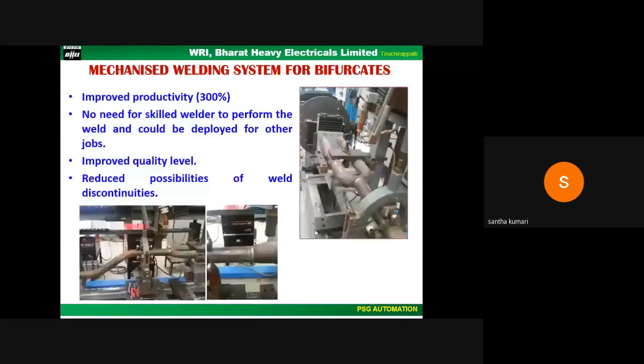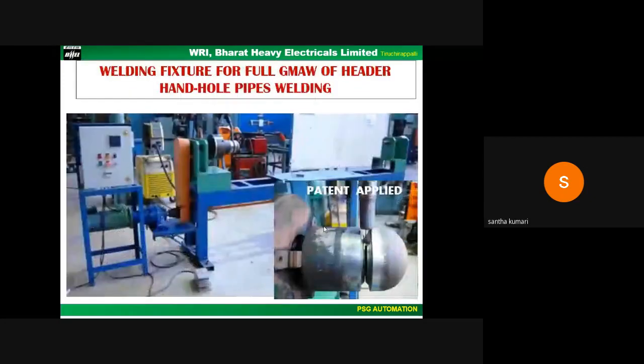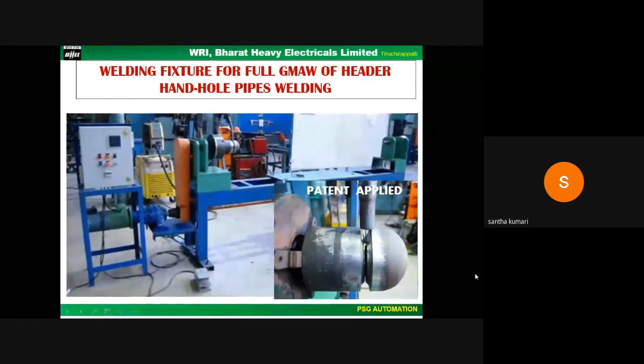Since the tubes will have deviations in all three axes, aligning them in the joint area was achieved by making a flat bed. By implementing this system, the productivity has increased by 300%. This is another automation: welding of a hand-hole pipe with a dished end. You can see the image here.